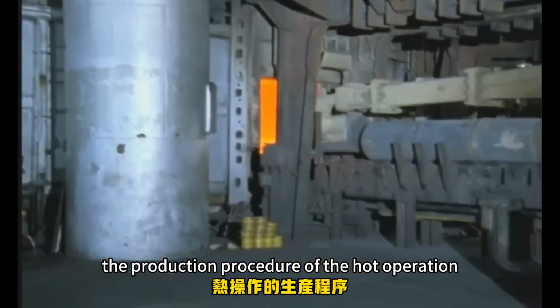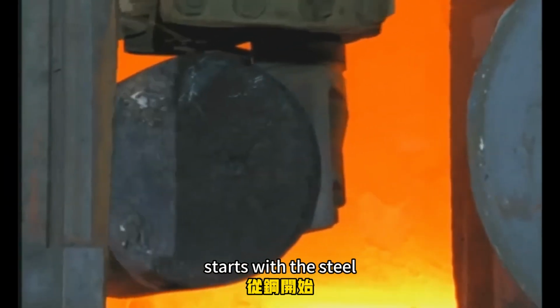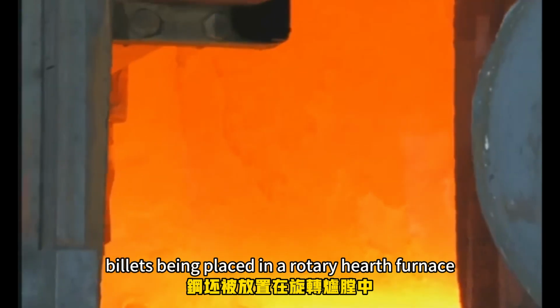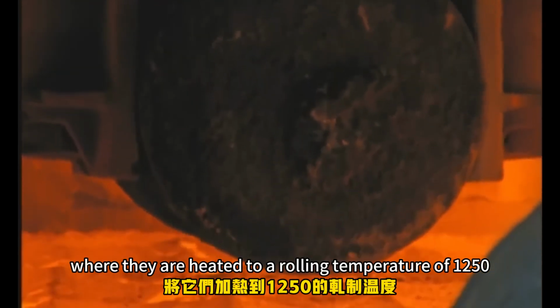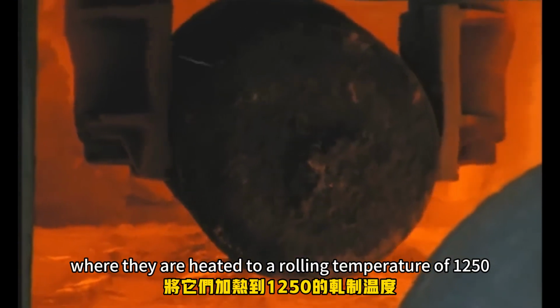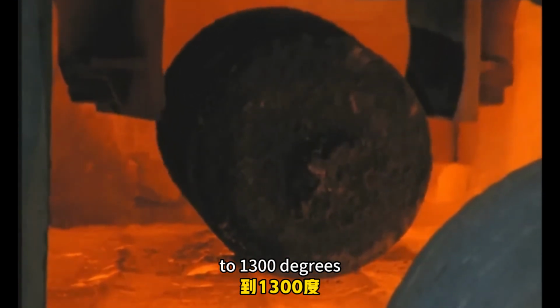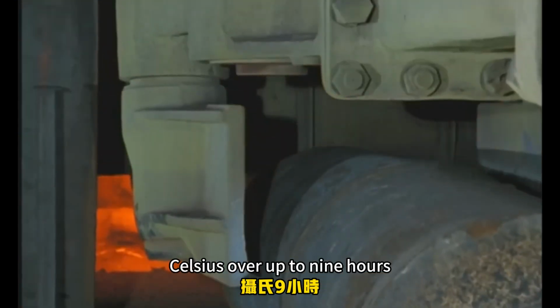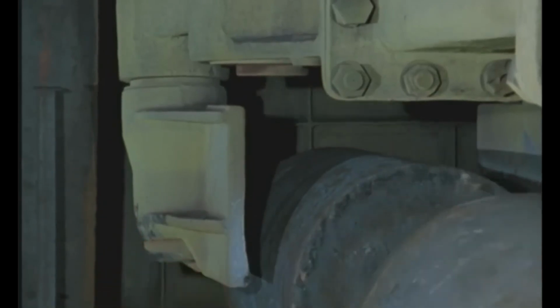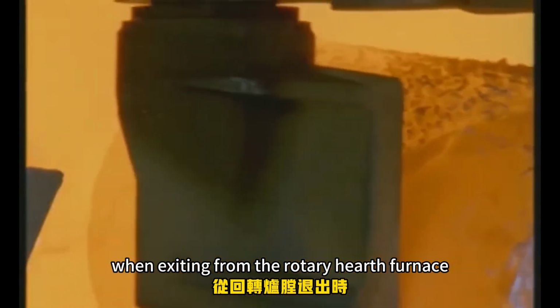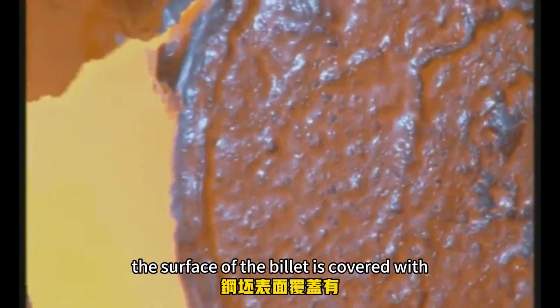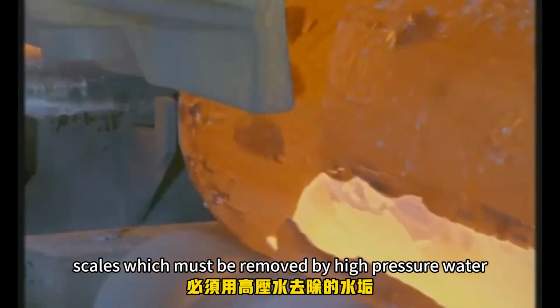The production procedure of the hot operation starts with the steel billets being placed in a rotary hearth furnace, where they are heated to a rolling temperature of 1250 to 1300 degrees Celsius over up to 9 hours. When exiting from the rotary hearth furnace, the surface of the billet is covered with scales which must be removed